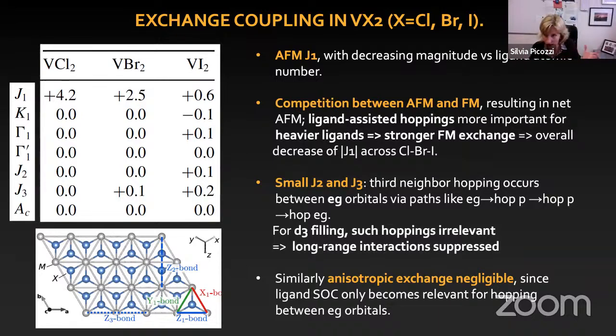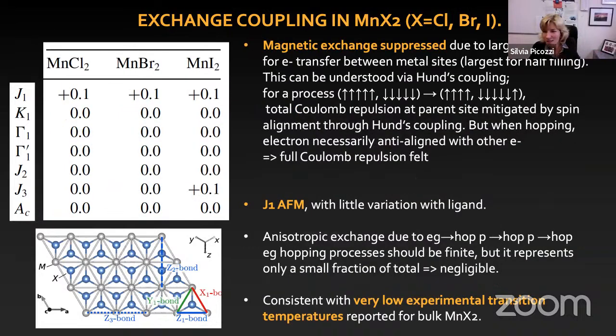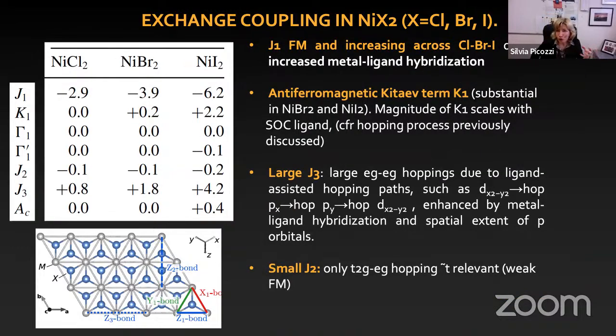Here you don't have any eg, of course, because it's d3, just t2g in the majority shell is filled, and so you don't have an anisotropic exchange. Also, manganese has a very small exchange in general, and no anisotropic exchange. So the d8 is really crucial. So maybe one should explore other d8 systems to have a sort of large anisotropic exchange.